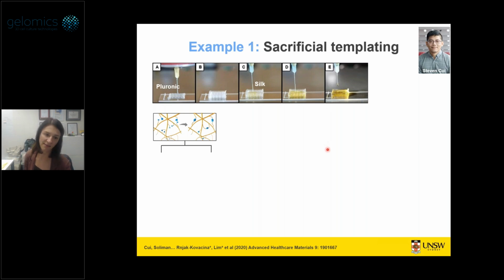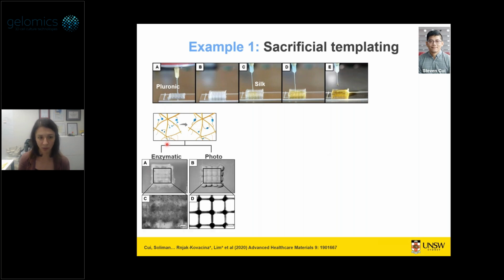And so we wanted to ask whether we can get high resolution structures by sacrificial templating silk on top of Pluronic. And we tried this using both the enzymatic approach, using HRP cross-linking of silk, and the photo-initiated approach, where we're using that ruthenium cross-linking of silk. And as you can see, in the presence of ruthenium photo cross-linking, because it happens very quickly, within 30 seconds, we can get very nice high resolution structures in silk on that Pluronic, whereas with the enzymatic cross-linking, we're not getting that because the reaction kinetics are so slow.